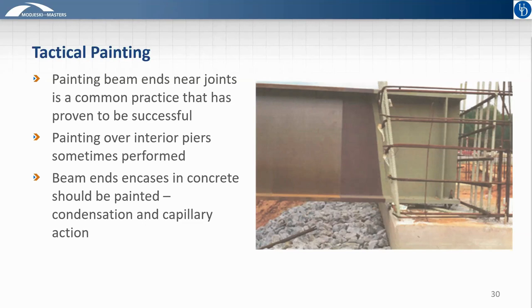which then sort of wicks into the area between the steel and the concrete through capillary action. And it doesn't take much moisture over many days before you start to have a problem here with localized corrosion. So that's the reason why you need to paint your weathering steel where it's embedded in concrete. Note that this doesn't apply to top flanges that get embedded in decks. The issue has never been seen in that region, or at least not to the extent that it's been seen in other areas.